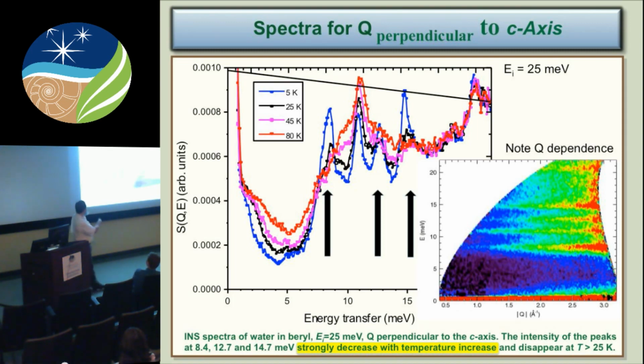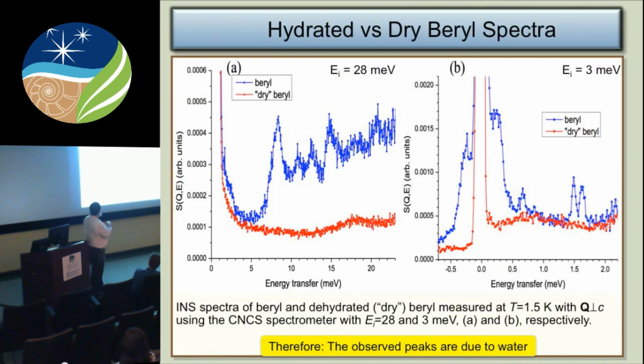However, if you look here, there's 5 K, there's 25 K, and by 80 K this is gone. The same is true here. In these peaks, we show a strong decrease of the intensity of the peak with temperature. In INS, you tend to run these spectra with different initial energies because it gives you greater detail over the range you're looking at. So the incident energy changes. When we go to lower energies, we also see that down in here, there are actually several more peaks that do the same thing. So the question is, what's going on?